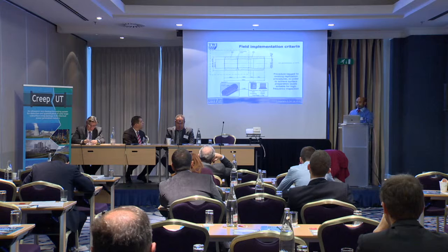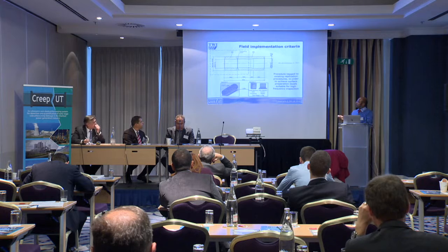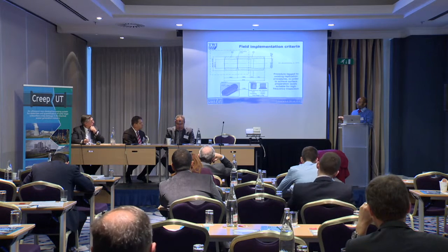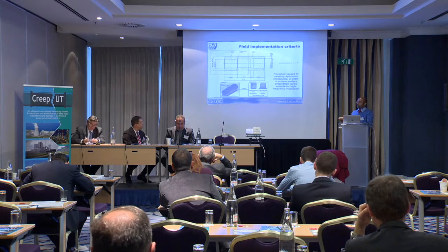And we also decided in consultation with SSE at the time that we should look at butt welded components, which are representative of the main steam line piping system, because they experience very high temperatures that approach supercritical levels, as well as having a geometry that we could deal with in the beginning without having the issues of the branch welds of a header system or a cooling system. So that's the component that was focused on, and that's an exact diagram of a pipeline system inside Ferrybridge.